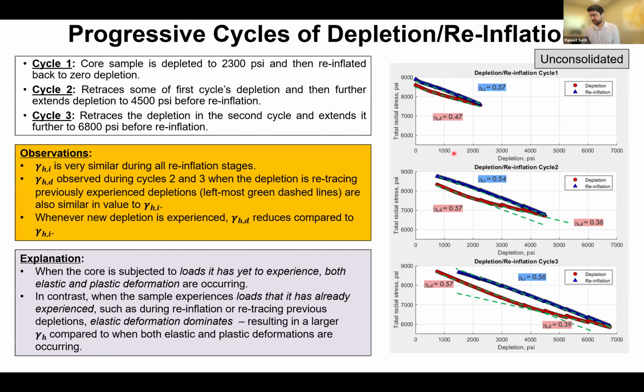The second thing that is also extremely interesting is whenever we are retracing the depletion in a previous cycle, so that would be this part in cycle 2, where we're going through the same depletion as the sample had previously seen in cycle 1, and here, where this part of depletion is retracing the depletion that the sample had already seen in cycle 2, the depletion coefficient is very similar. It's actually the same and very similar to the injection coefficient. So this is very interesting. Only when the sample is subjected to a depletion that it has not seen before. Obviously the first time you're depleting, it's the first time it sees that depletion, the depletion coefficient is different.